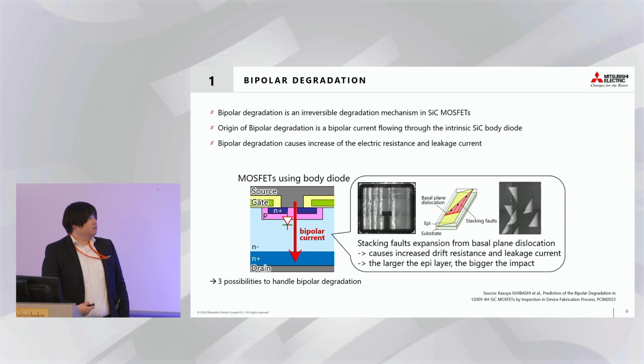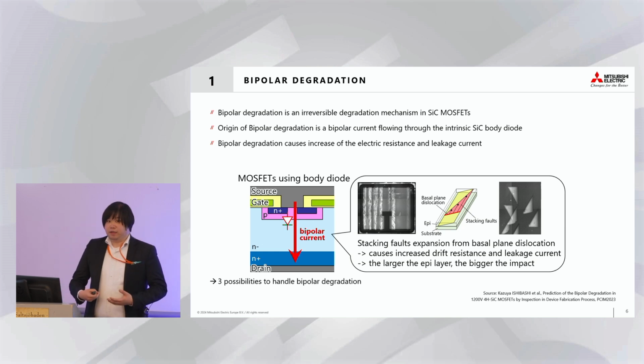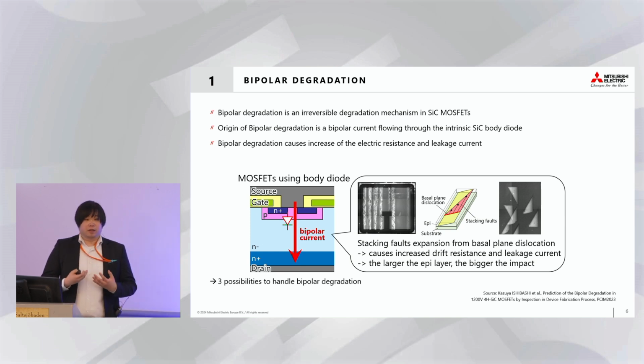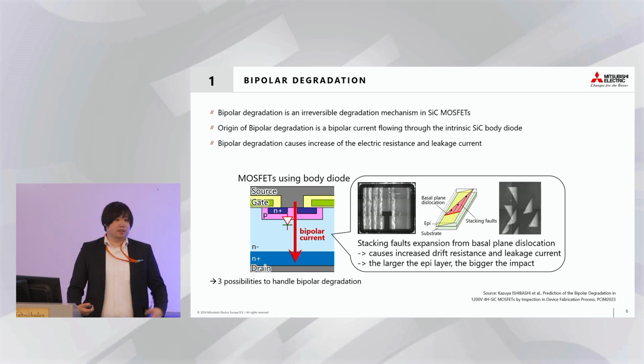And this is especially critical: the larger the epi layer is, the bigger the impact will be. And of course, for higher voltage ratings, so just high voltage modules like 3.3 kV or even higher, this becomes more critical. And there are basically, let's say, three possibilities how to handle this bipolar degradation mechanism.